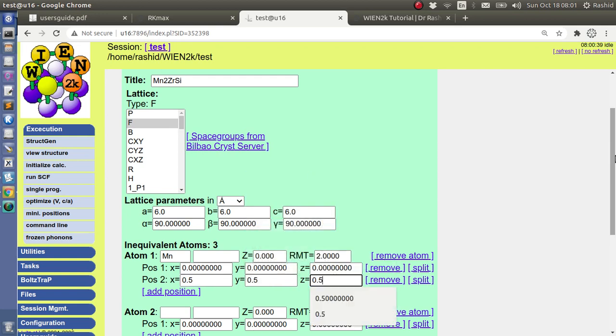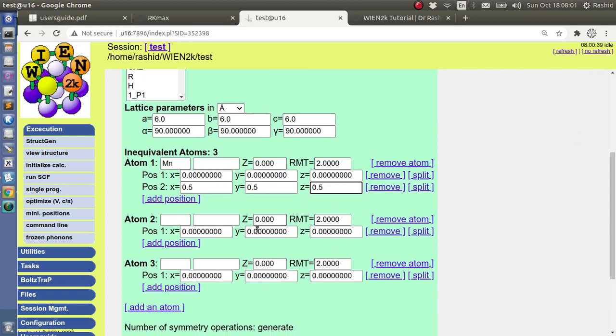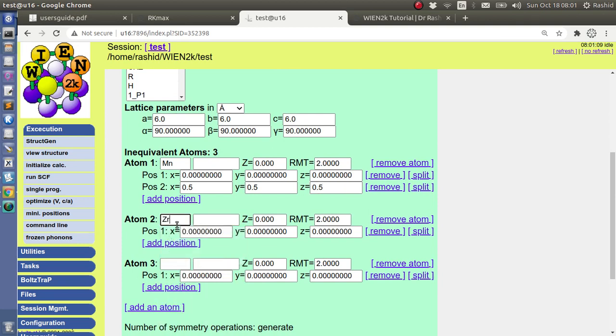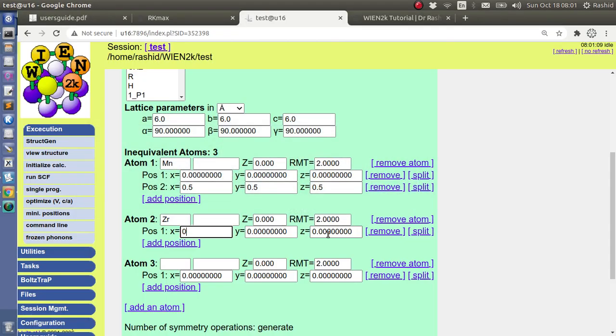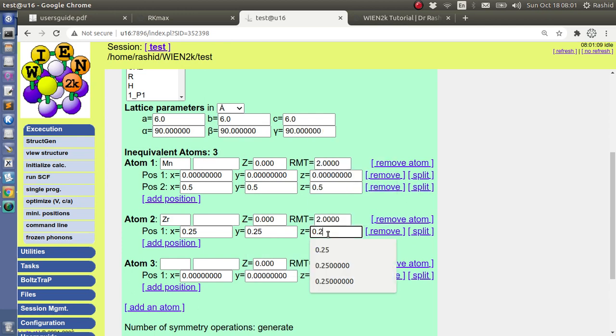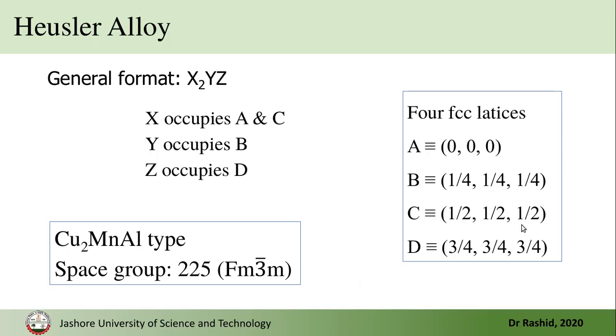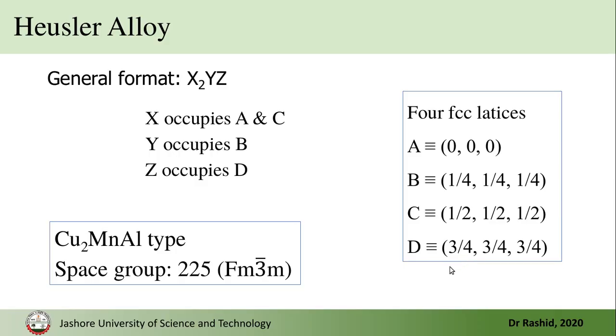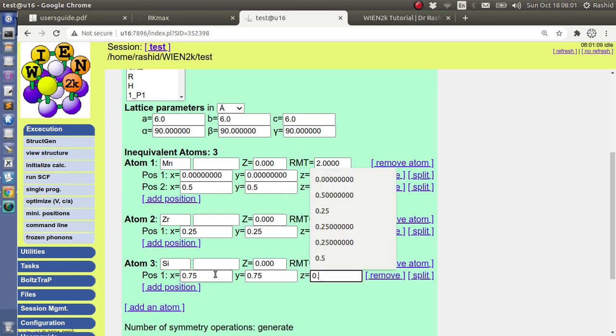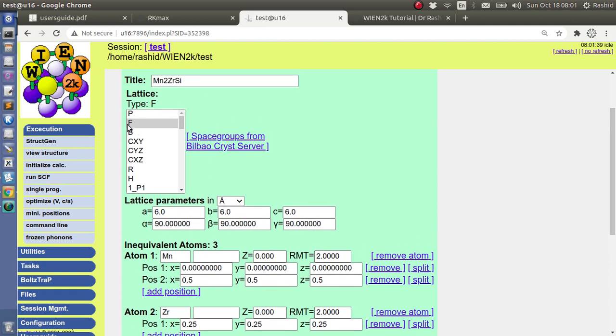And for the zirconium, let's put the atomic position. It will be B (0.25, 0.25, 0.25). And silicon (0.75, 0.75, 0.75). Remember at this point we will select space group F because these are all face centered cubic.